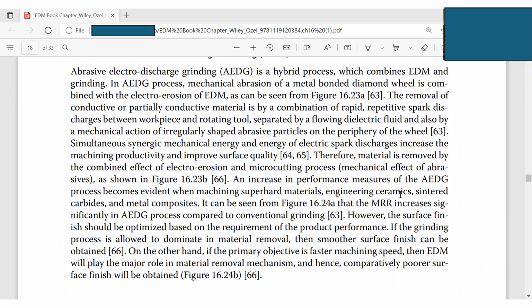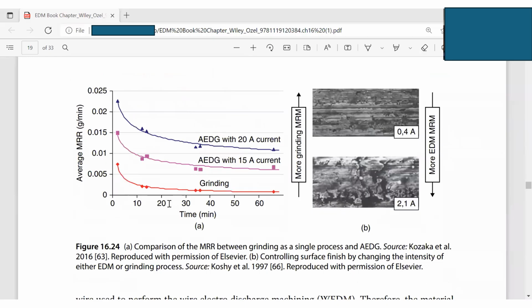For example, engineering ceramics, sintered carbides, and metal composites. It can be seen from this other figure that the MRR increases significantly in this combined process when compared with the conventional grinding. So you can see it here. This is time, this is the average MRR. Here is a conventional grinding. Here is an abrasive EDG with 15A current, and this is with 20A current. This 20A current is for the EDM. You can see the average MRR can be improved substantially.